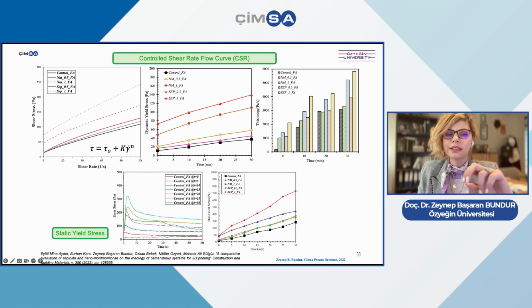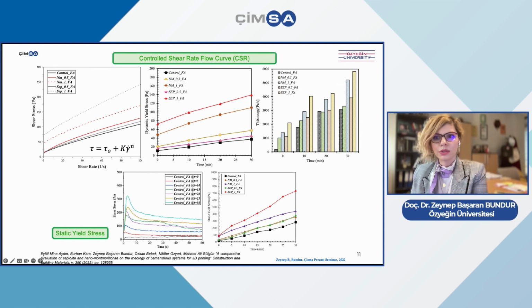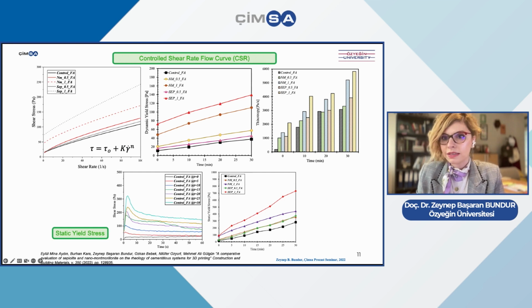In that sense, we can have shear rates, as you can see here. It's a little bit specific, but you can see the values. When we look at quality control for 3D printers, we can have shear and slump and pressure resistance for standard concrete as well. So that's actually the basis. The challenge is that there is no standard quality control test as well. So we can only note down the rheological properties of the printed concrete. You can see here how the rate of viscosity and the elasticity modulus and similar values are printed.